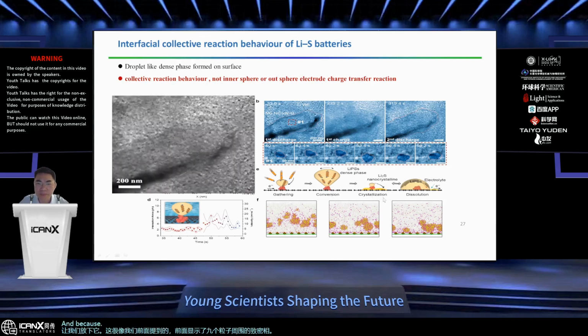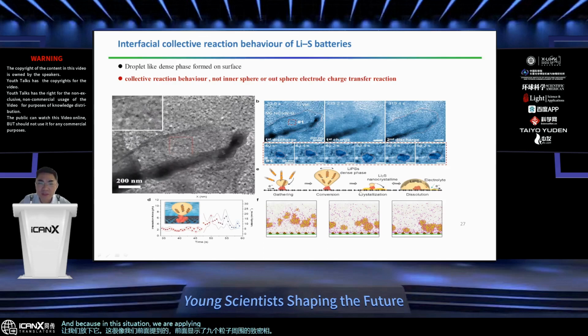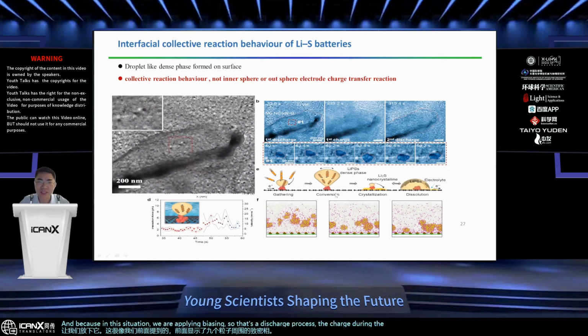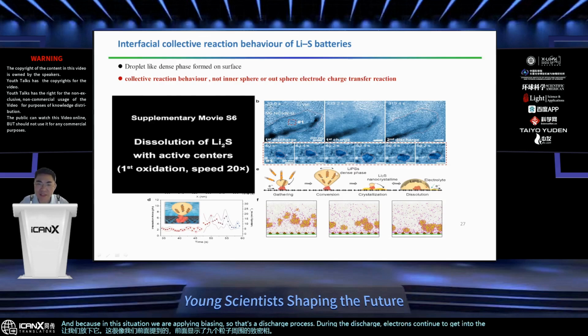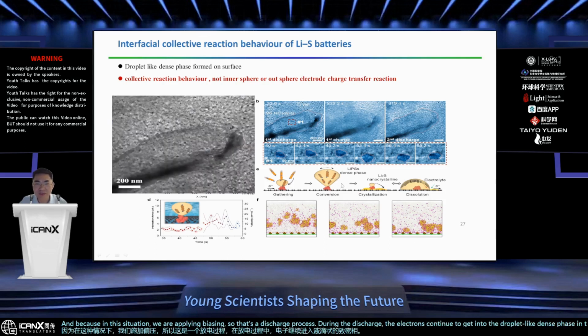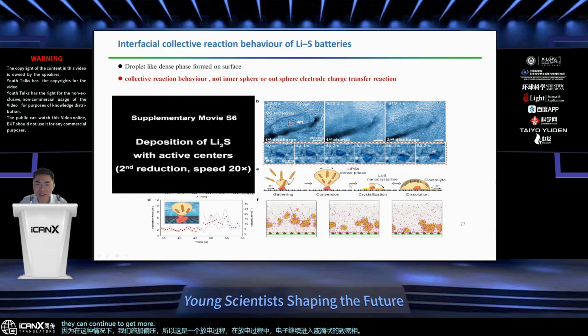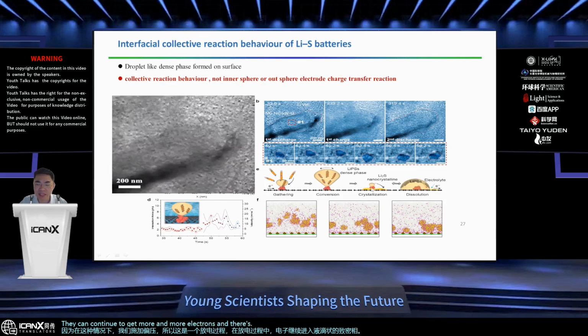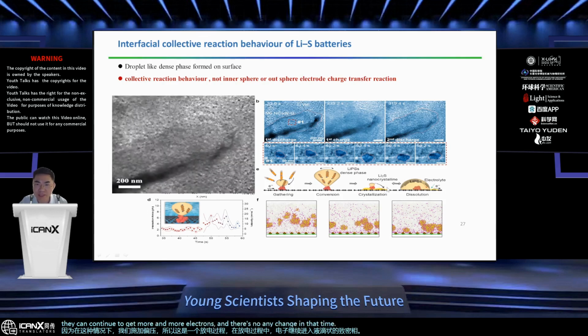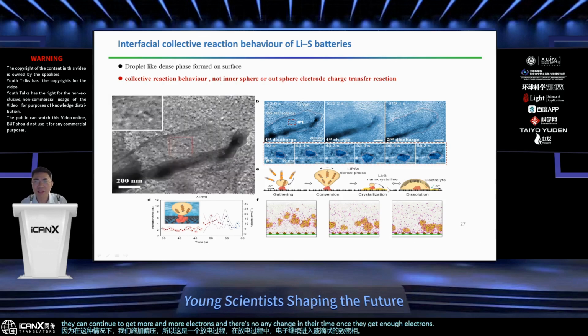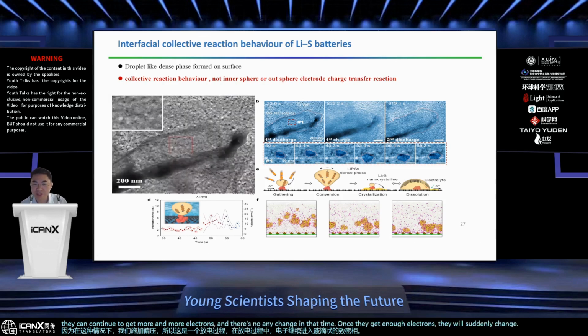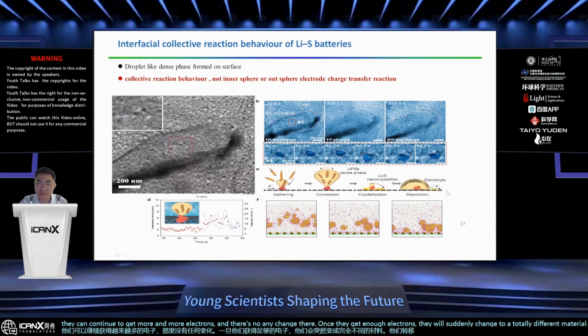Because in this situation we apply biasing, that's a discharge process. During the discharge, electrons continue to get into the droplet-like dense phase. In this bubble-like dense phase, they can continue to get more and more electrons, and there's no change at that time. Once they get enough electrons, they will suddenly change to a totally different material. They transform to Li2S nanoparticles.